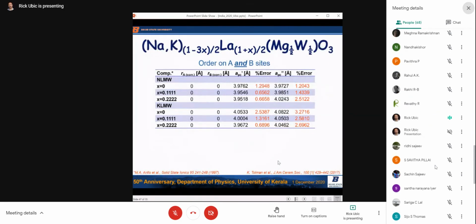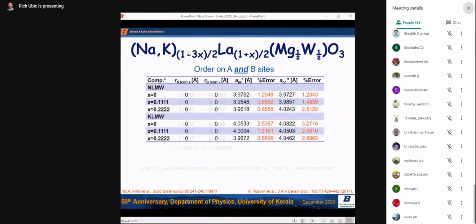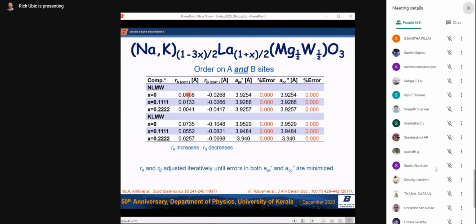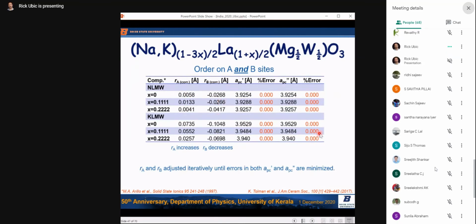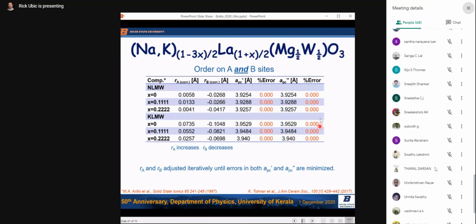Okay. Sorry, I'm rushing a little bit. We have materials, a few, that have ordering of both A and B sites. So we have these guys up here. And so we'd expect, again, correction factor is positive for A, negative for B. And the errors actually do identically go to 0 because you have 2 parameters to play with, so it's pretty easy to make them go to 0.